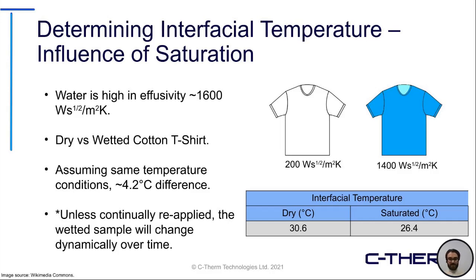Now, when you're dealing with wetted textiles, this is another thing that has come up. There are a lot of variables that will come into play when you're doing wetted testing, related to the fact that a wetted material will be continuously changing dynamically over time. If it's initially wetted, as soon as that fabric becomes saturated, it will begin the drying process, the evaporation of the water, the spreading of water throughout the fibers, pulling water away from the measurement area if you're having that on top of the sensor. A lot of these things will come into play when you are doing these types of analyses, so it's really important that you're controlling for that and taking note of what's occurring during your measurements.